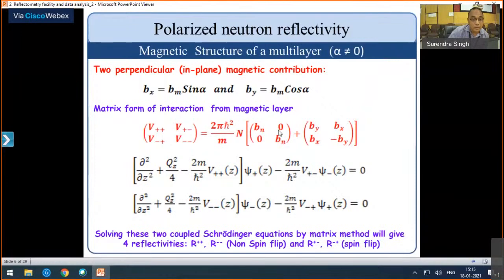In this case, we have only the perpendicular part, Bm sine alpha, this Bx, and we don't have any nuclear part for this. So whenever we have a spin flip reflectivity from the magnetic sample, it is purely the magnetic component.